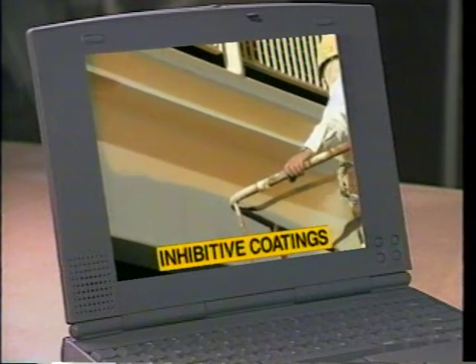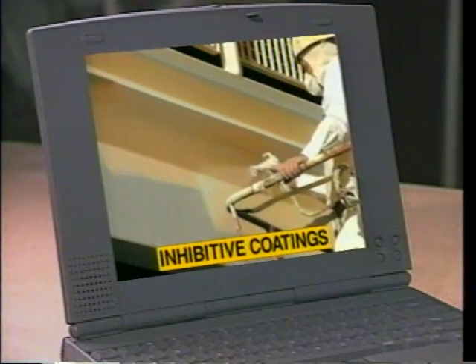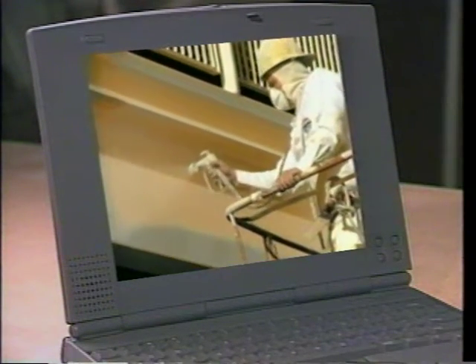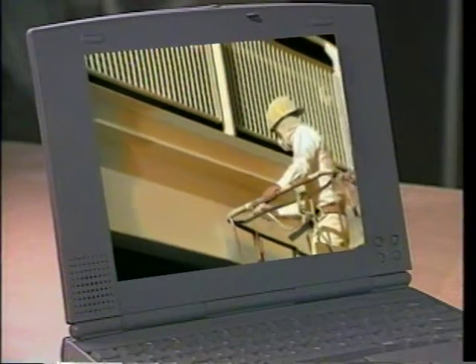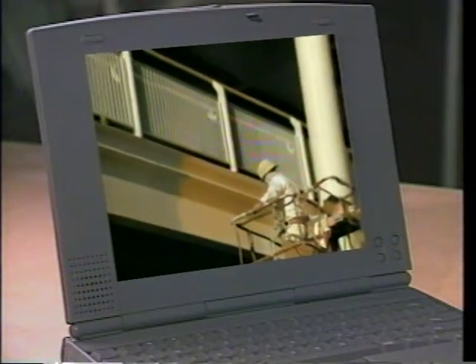Inhibitive coatings contain certain additives or pigments that have corrosion-inhibiting properties. These inhibitive pigments are partially soluble in moisture and work by different mechanisms, but essentially they provide a coating that is more stable than the metal substrate they protect. In the past, red lead and zinc chromates were common inhibitors, but due to environmental and health concerns, today's high-quality coatings contain more environmentally friendly inhibitors like zinc molybdate and zinc phosphate. And finally, some coatings are called sacrificial because they include metallic particles that are anodic.